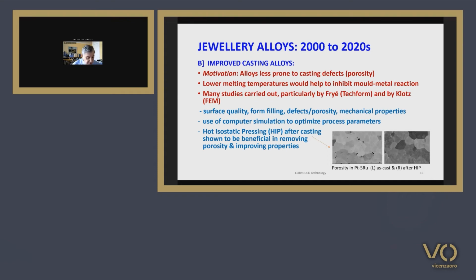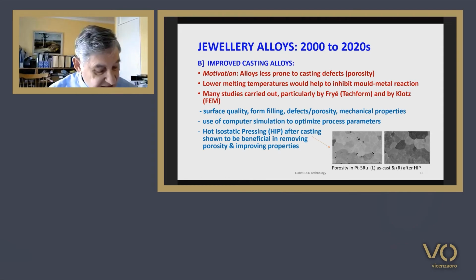Work carried out by Frié at Techform and Klotz and co-workers at FEM in Germany has focused on which alloys are best in terms of casting porosity, form filling and surface quality, and establishing the mechanical properties of cast alloys. The use of computer simulation of the casting process has also assisted in optimizing process parameters in casting. Frié in particular has shown the benefits of a hot isostatic pressing treatment after casting in removing porosity from castings and improving the mechanical properties.